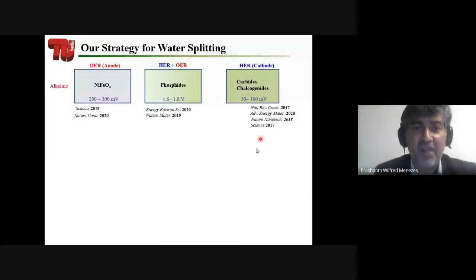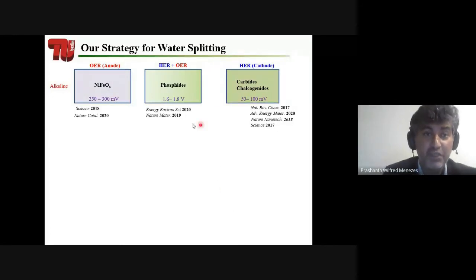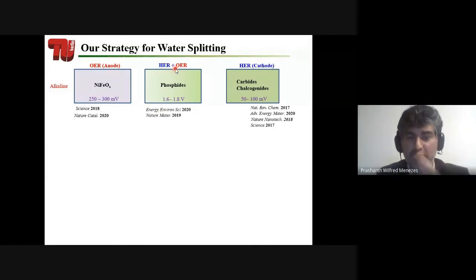So this is our strategy for water splitting. If you have a two-compartment cell, this is the anode and this is the cathode. Usually nickel iron based catalysts have been used for alkaline electrolysis. So this is the potential for the hydrogen evolution reaction, and this is the cell potential for overall. That means we are producing hydrogen evolution and oxygen evolution at the same time.